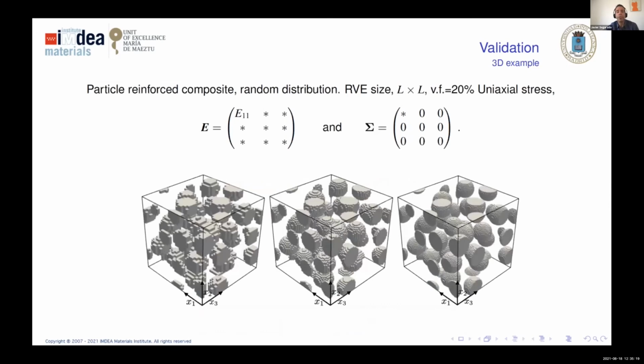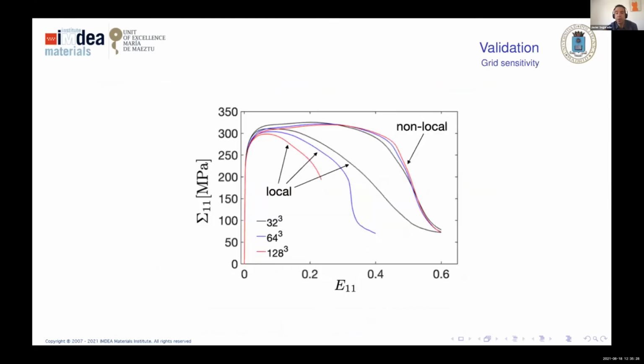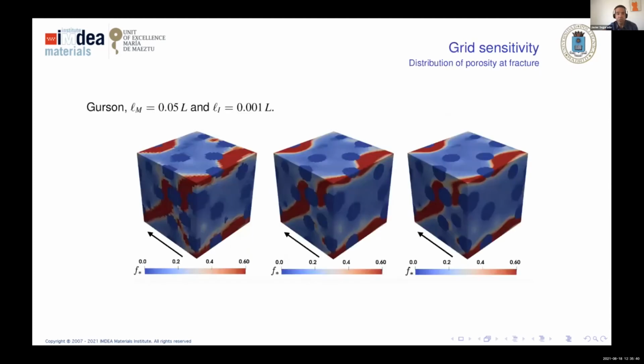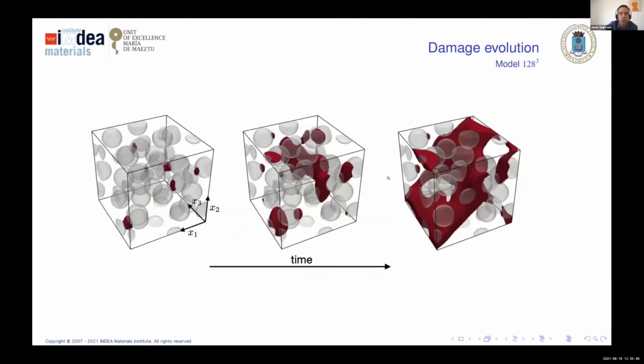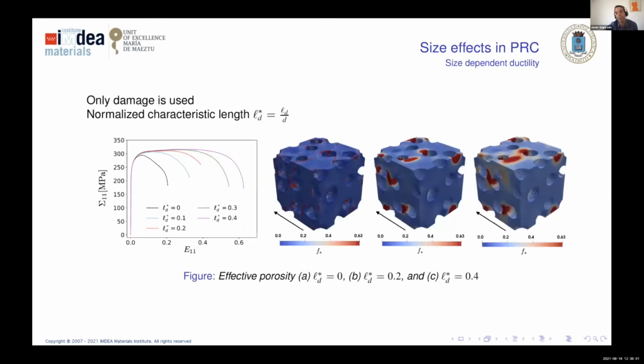Okay, let's go to 3D. Three different sizes. Now the RVE is a particle reinforced composite with spherical particles that are randomly located, 20% volume fraction, and the same. The original local model has a size dependency, while the non-local model has the same behavior for all the different discretizations. And we are able to model how the band locates, and we are also able to show how the band evolves. So we have developed a very nice model that allows us to do 3D simulation of fracture or damage in this case, considering complex microstructure.